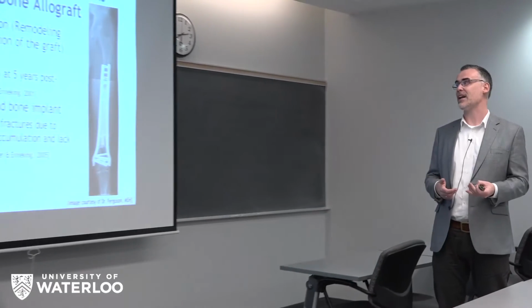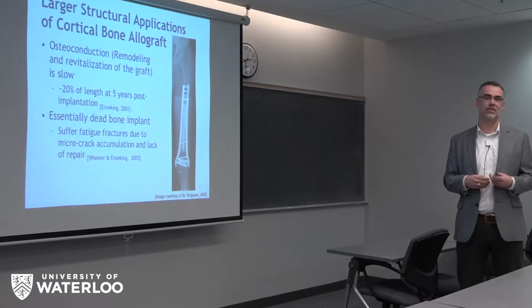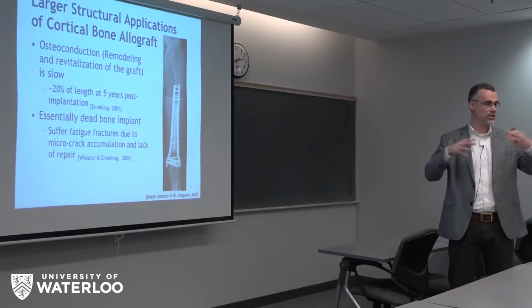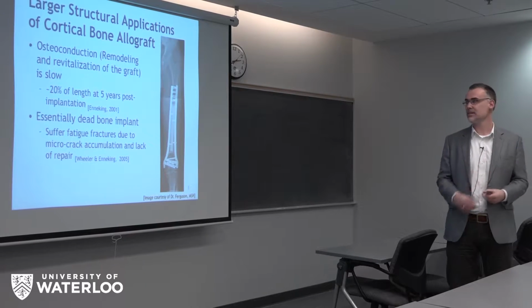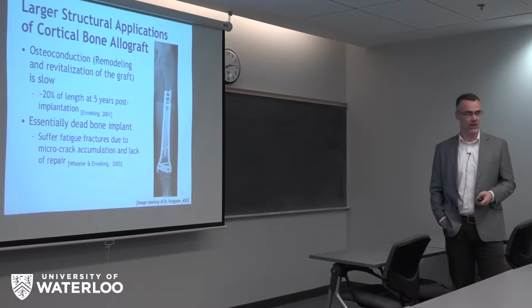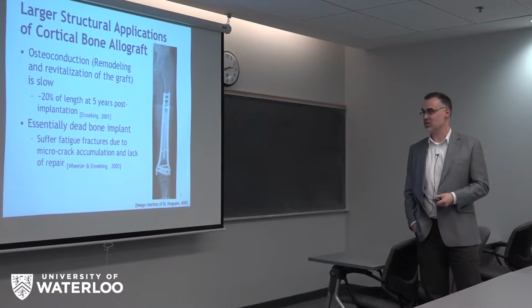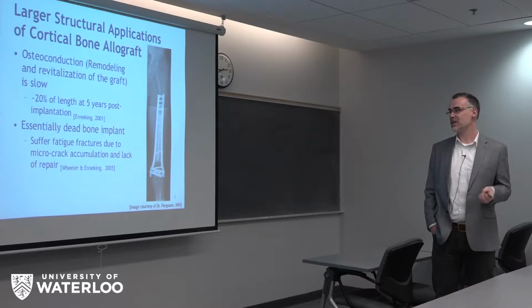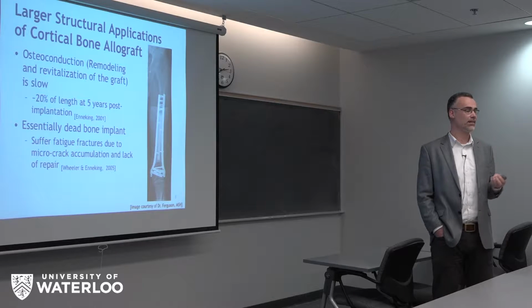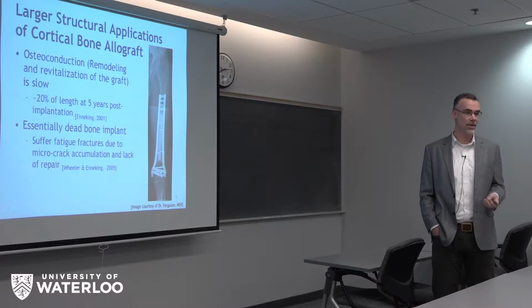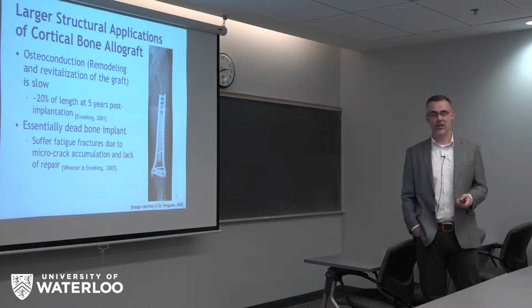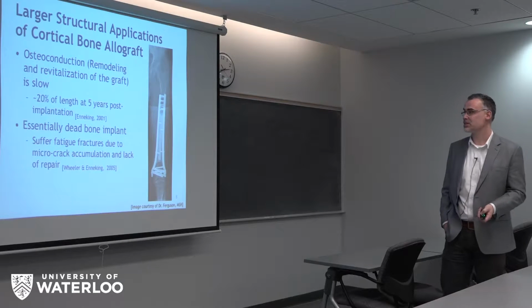And so what we're really talking about is using a piece of dead bone as an implant. And what comes with that is that you have the need for osteoconduction, the host bone, to grow into the implant, into the dead bone, but this is really slow. And so you're essentially dealing with a dead bone implant, and it is a microcracking material. So over time, under physiological loading, it will accumulate microcracks and eventually fracture.